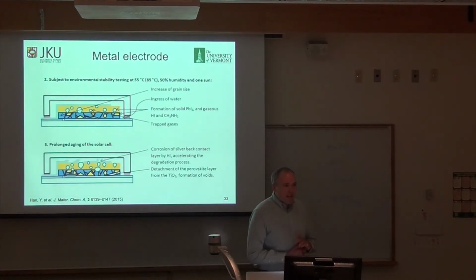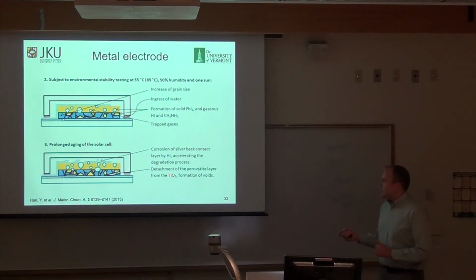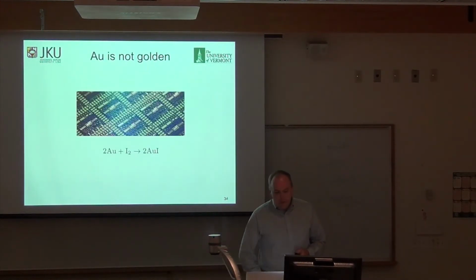But what do we do about the metal electrode? Because as we said, if any water touches this perovskite layer, iodide comes out of the perovskite and bubbles up to the surface, which causes the electrode to delaminate. Which seems like an insurmountable problem.